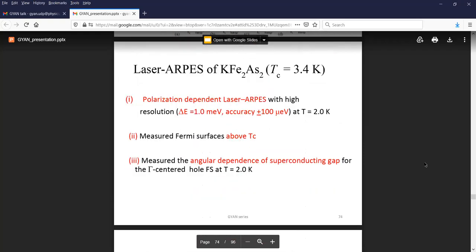This demonstrates the power of doing momentum-resolved angle-resolved photoemission. I go to the last example, which is polarization-dependent ARPES of potassium iron arsenide, which has a very low TC of 3.4 K. We needed very high accuracy because of the low temperature. We could do experiments at 2 Kelvin with a resolution of 1 milli eV and an accuracy of plus/minus 100 micro eV. One measures the Fermi surfaces first, then the angular dependence of the gap.